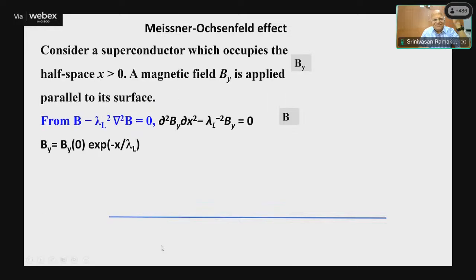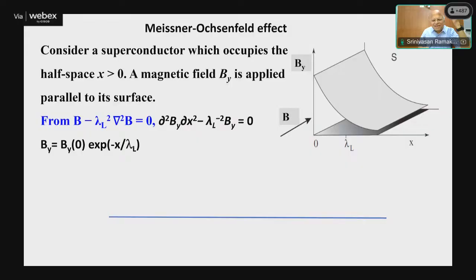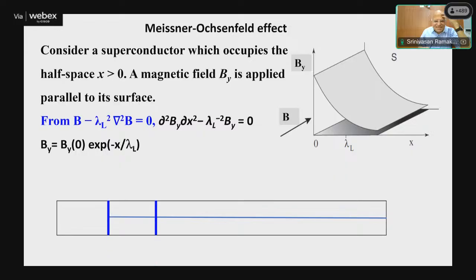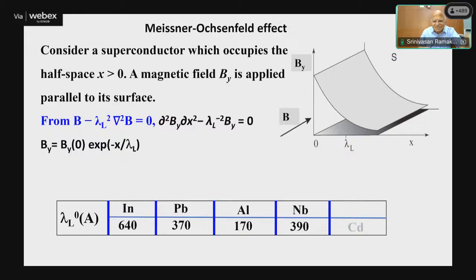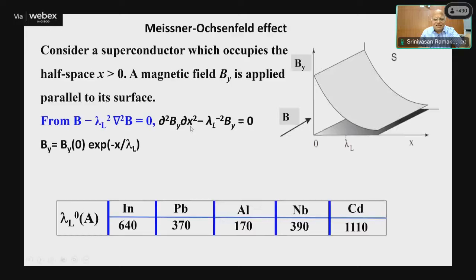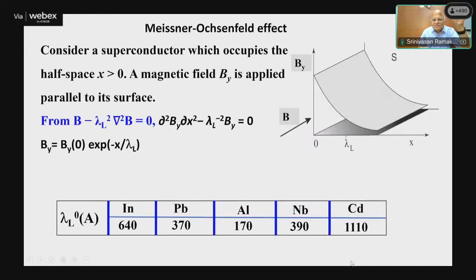And he was able to give an expression for a simple slab, B as a function of distance, and this lambda L is the London penetration depth. People quickly measured the penetration depth for various superconductors: indium, lead, aluminum, niobium, and so on. So London was able to explain how the magnetic field penetrates into the superconductor.